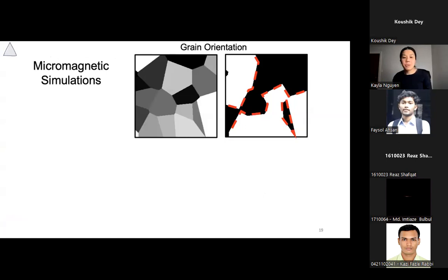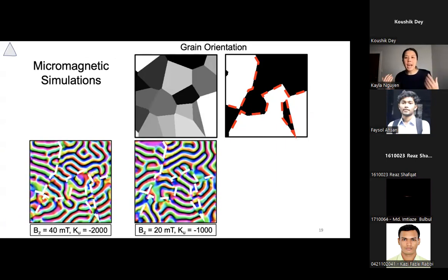So how do we prove that this is also true? What we do is we go back to micromagnetic simulations. So we take a bunch of grains and we randomly added different crystal chiralities to the grains. And then we also added different signs of the Dzyaloshinskii-Moriya interaction within this material as well. So we have it under different field conditions.